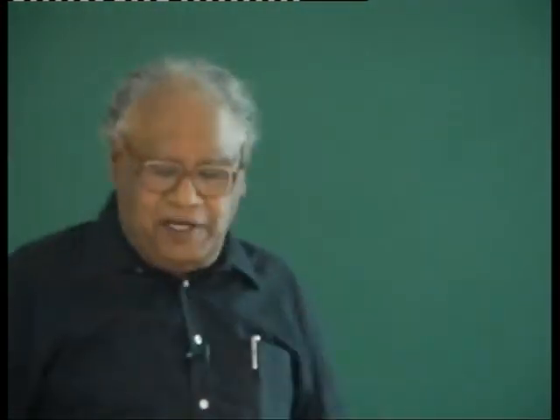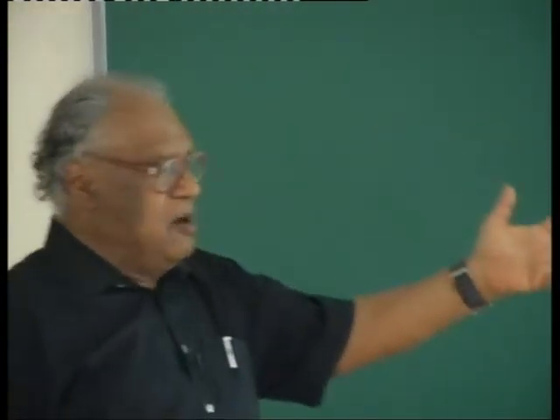So what is the origin of ferroelectricity? These are the things we are looking at, and Professor Wagner, who is not here probably, is a theoretician who is working out some theory on why it is so, and a lot of work has been done. One of the simplest explanations right now is that there are two magnetically inequivalent Fe3+ ions. As I told you, there are two different types of magnetic interactions. One is ferromagnetic and there is antiferromagnetic interaction between the two octahedral sites of iron. That, in addition to the disorder that is there, which I didn't talk about in the beginning, is probably responsible. So basically it is breaking of inversion symmetry. Breaking of inversion symmetry is what is causing this ferroelectricity, according to us.